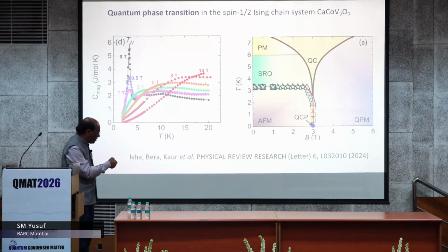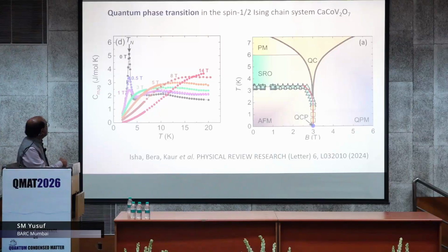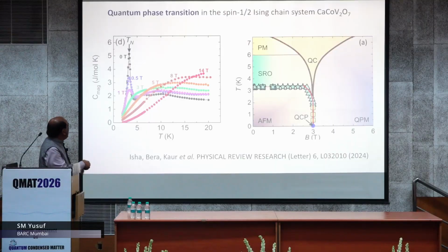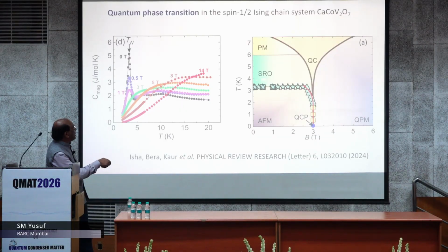If you go a little beyond, this is the fascinating way, the specific heat, magnetic specific heat, we have plotted here by correcting the lattice one, and what we do here as a function of temperature at different applied DC field, and this is my ordering temperature, so-called Tn. When there is zero field, we do have this specific heat peak at T equal to Tn, but when you increase the field, this peak disappears,